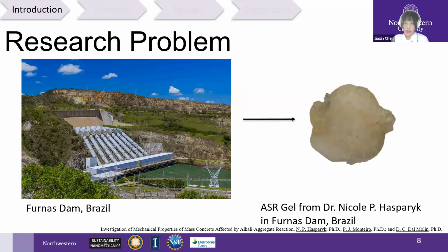So here is a picture of Furnas Dam in Brazil. Our samples were actually collected from the Furnas Dam in Brazil by Dr. Nicole Hasparyk and Professor Paulo Monteiro. I will give a quick introduction of this dam and its history related to ASR. The occurrence of the alkali-aggregate reaction in the concrete of the Furnas Dam was first noticed in 1976. The areas of greatest concern were the cracks on the top of the spillway columns, in the anchorage blocks of the water conduits, and in the powerhouse.